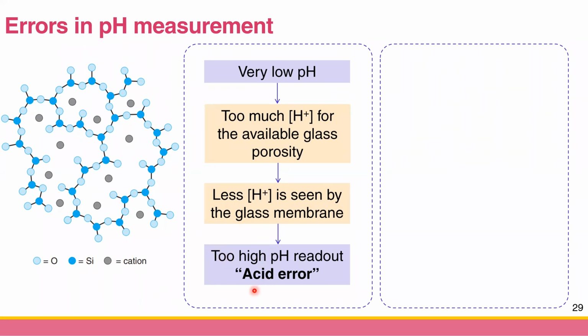So we call this acid error. For example, if your sample has the pH of 1, maybe you're gonna get some value like 1.2, something like this. This is because some of your protons cannot be seen by your glass membrane. Your glass membrane has limited pores to bind with your protons. So this is acid error.